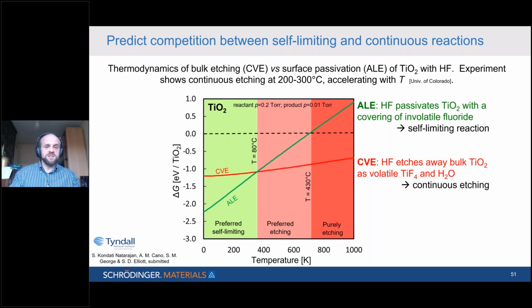If we look again at the 0 Kelvin energetics, so at the very left-hand side of this graph, you can see the free energy for the ALE, the green curve, is much, much lower. So the energetically favorable situation is passivation of the surface at low temperature. But obviously, with the effect of temperature, the situation changes. And above about 80 degrees Celsius, we predict, the continuous process takes over. What happens is the entropy penalty is just too high for ALE. And instead, entropy favors the desorption of material and the etching away of material as TiF4 and H2O. So the CVE curve, the etching curve, becomes more favorable from 80 degrees C onwards.